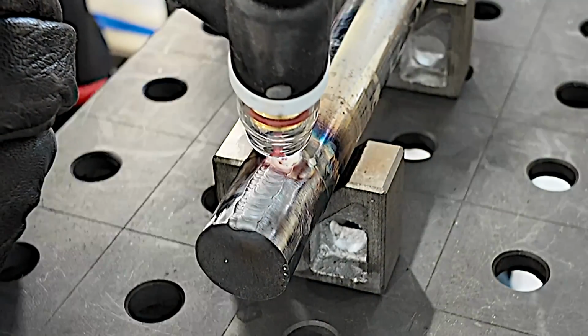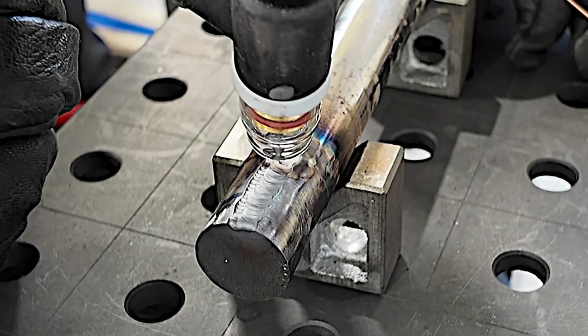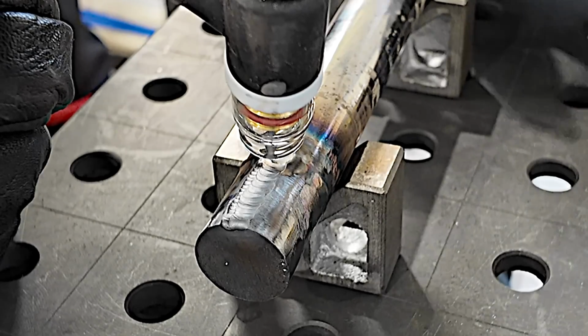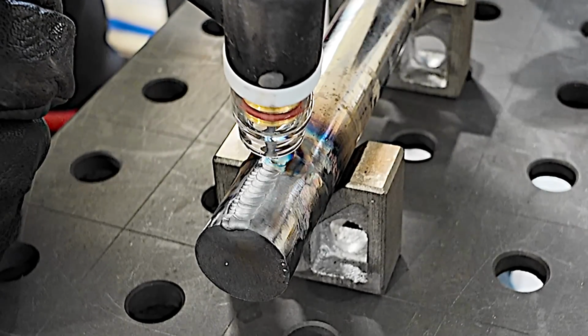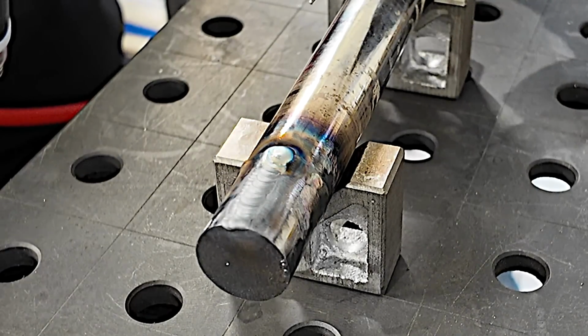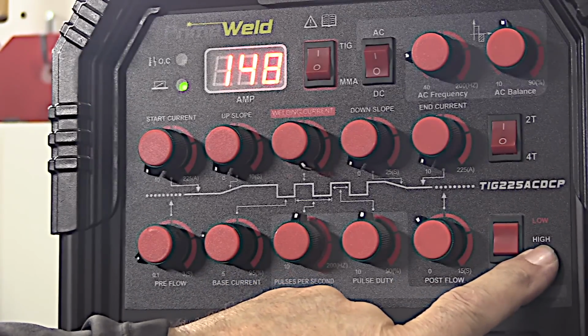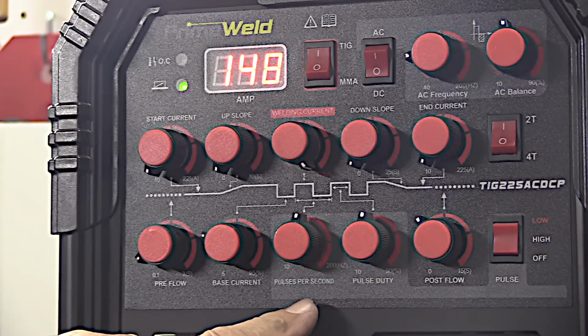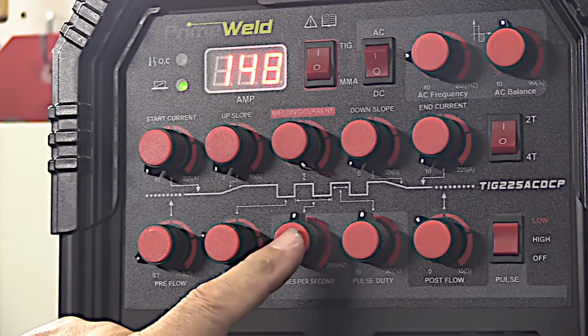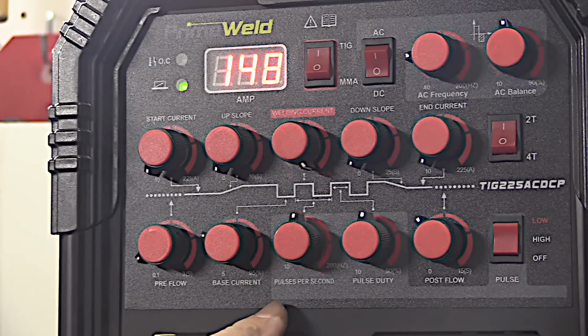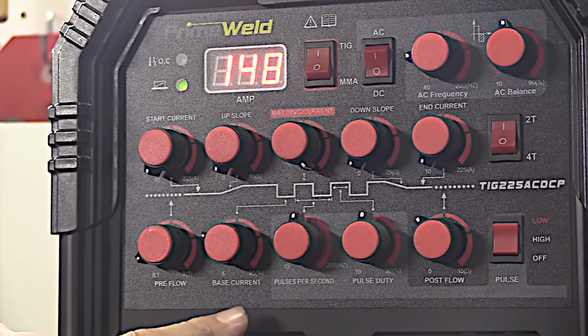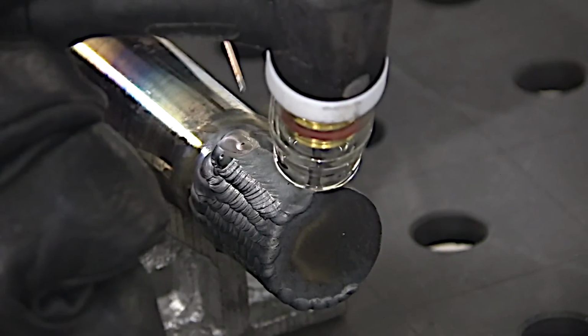And again, you're just trying to stack one bead almost exactly halfway over the previous bead so that you don't have any low places that won't clean up when he puts it on the lathe. And if the beads start swimming around and wandering with you, one thing you can do to cure that is use the pulse setting on your machine and a high pulse rate, something around 100 to 150 pulses a second. When you use pulse like that, you have to increase your amperage. In this case, I used 100 pulses a second, 30% background, and 50% pulse duty. And this is the bead that yielded.